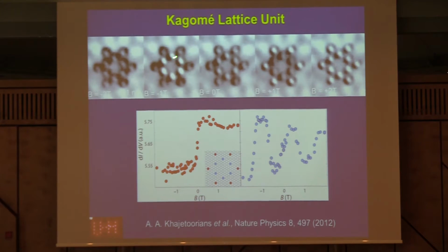And again, amazing is the fact that the single atom magnetization curves for the same atoms at exactly the same adsorption site look so much different simply because of the neighborhood, the interactions with the neighboring spins. And so in these single atom magnetization curves, we have a huge amount of information about these couplings.